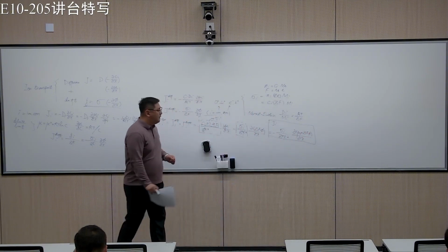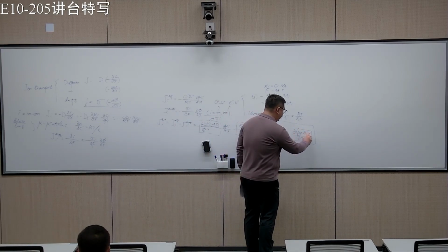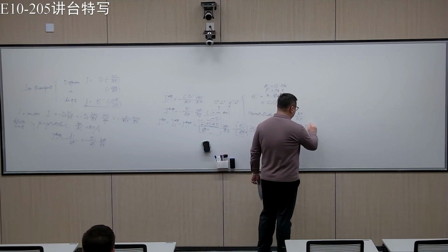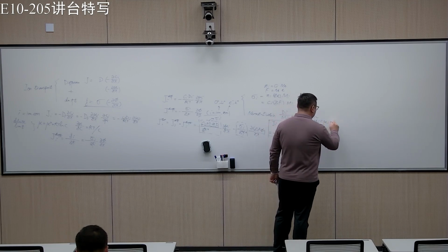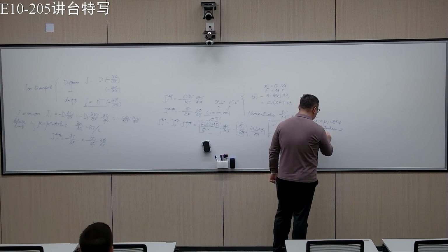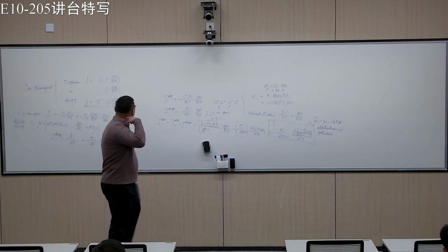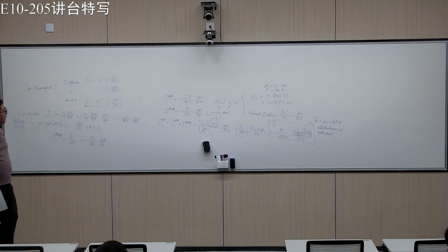You can see from this equation, what really matters is this part. This is the real driving force. We call it mu i tilde, being mu i plus Zi F phi, which is called the electrochemical potential. So we can go back here and add one more equation.